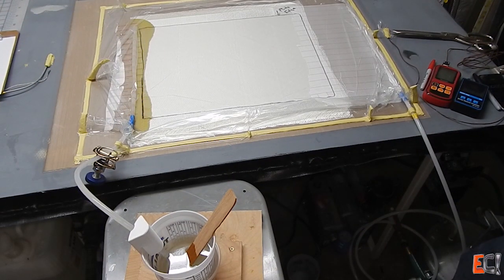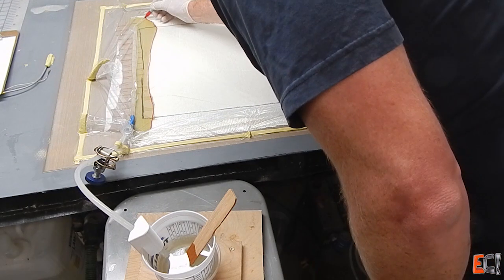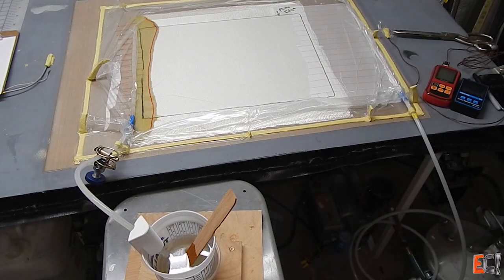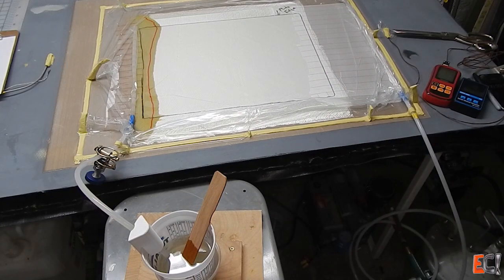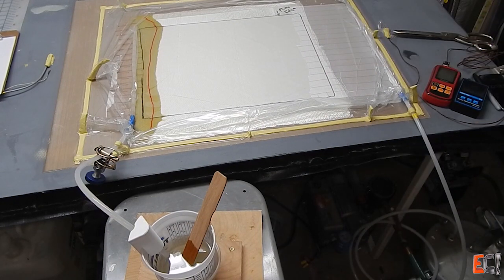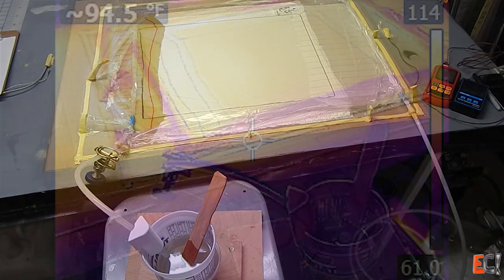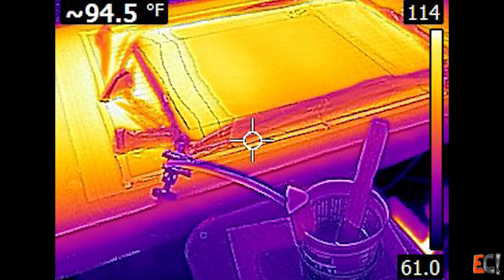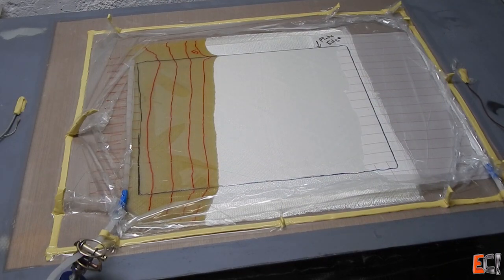And you can see on the back side, it's taking up that peel ply. Ideally, you wouldn't have that back there. That's just kind of asking for trouble with trapped air that then comes out and gives you problems later on. And you can see the thermal picture of it with the cold resin in the cup and the hot table.